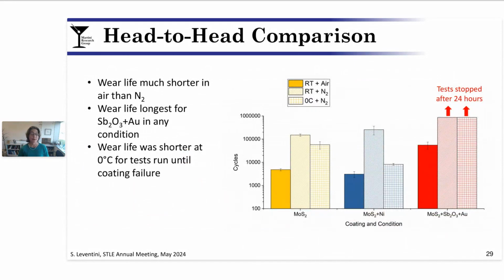Shown here is the complete data set. This is the wear life of these coatings at the 3 different conditions and the 3 different coatings. A lot to unpack here, but we can draw your attention to just a few points. First of all, the wear life, which are the solid bars, is shorter in air for any of the dopants. In addition, the antimony oxide gold wear life is much longer than that of the other 2 in any of the conditions. The 2 red arrows on the far right indicate that the test was stopped before the wear life was reached.